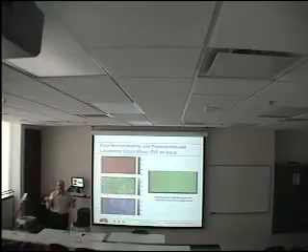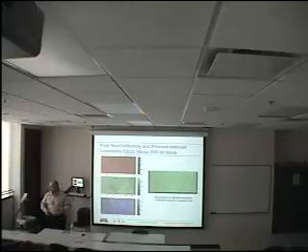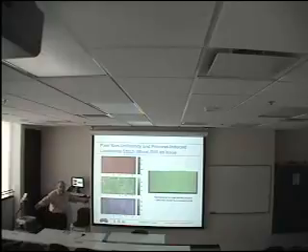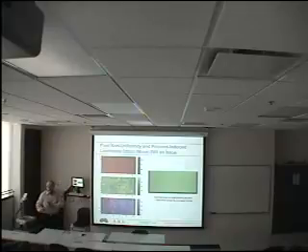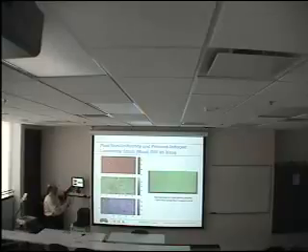Your eye cannot detect that. In fact, it's very difficult for your eye to detect a factor of 2 change in light. Eyes are very logarithmic detectors. You can see very, very dim levels, and outside, well, if the sun were shining, very, very bright levels. So you can see there's patches here that depend on basically as you spray this solution that you then dry out over a large area. The spray is not the equal thickness everywhere that you put it. And so these add up from layer to layer to layer, and you get non-uniformities like this. But you can see there's no similar pattern to all of these. Each one is different. So every layer has its own non-uniformity, and that shows up in these.